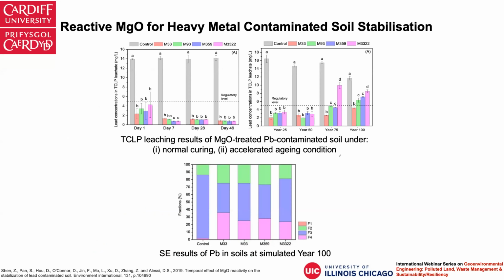Before going to these cementitious materials incorporating magnesia, I would like to first introduce some of the soil stabilization applications using reactive magnesia itself. Okay, so reactive magnesia, when it's in contact with water, develops brucite. Brucite does not produce a lot of binding. Using reactive magnesia at a certain dosage, you are actually only applying stabilization instead of solidification.